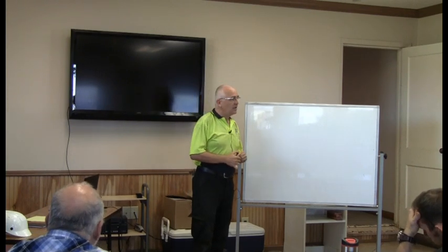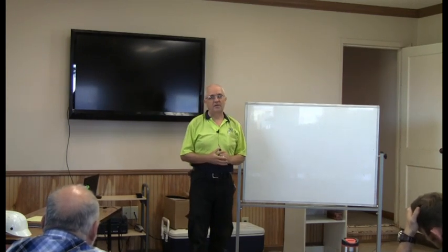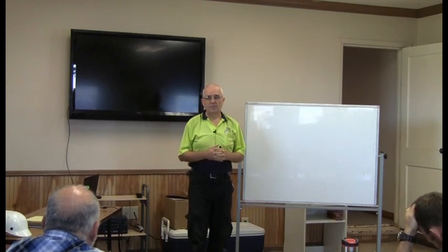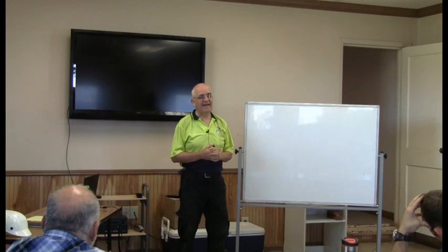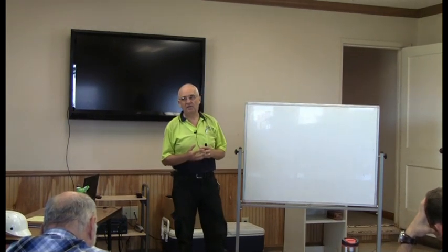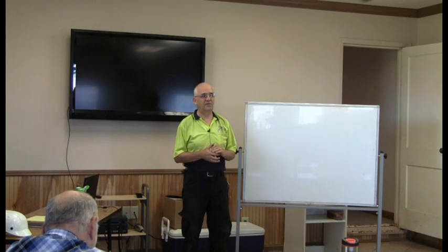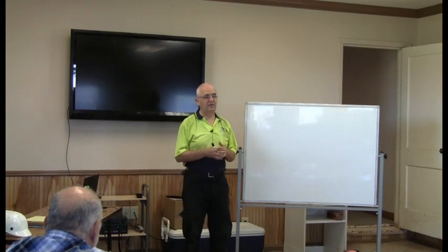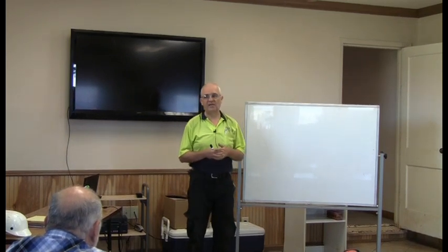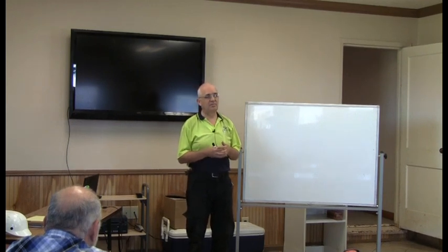When you look at the kiln, a lot of time people look at it with heat and energy primary. But it's not only that. In the kiln we need to supply energy, we need to supply heat, but we also need to supply air for various concerns. We need to cool down the product, we need to transfer energy, we need to burn out the crap which is inside of the raw material in the preheat, and that's not the heat, it's the air and the heat. So if we don't have the right amount of airflow through the kiln at specific areas, it doesn't work. No matter what we do with the burners, no matter what we do with excess air, etc., we can cheat with that, but we will never achieve an optimum operation of the kiln.